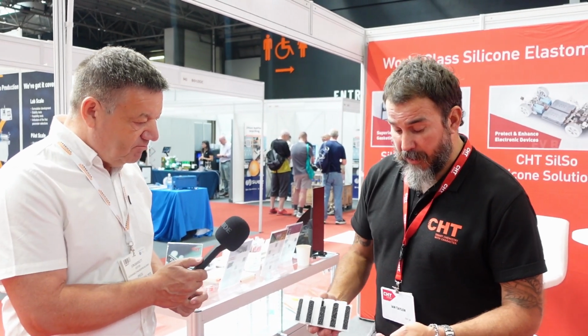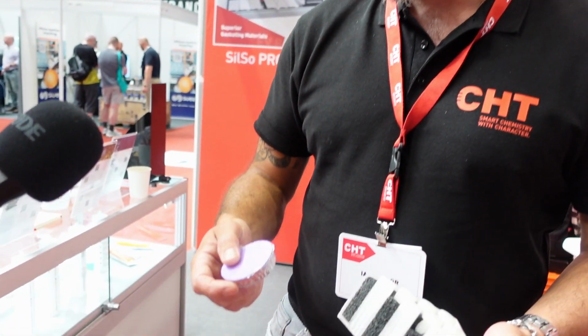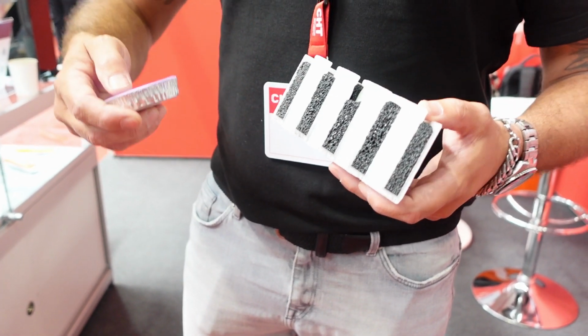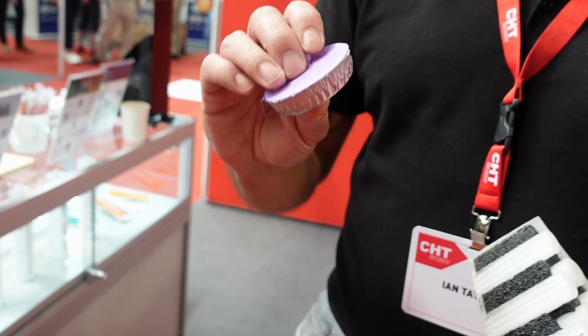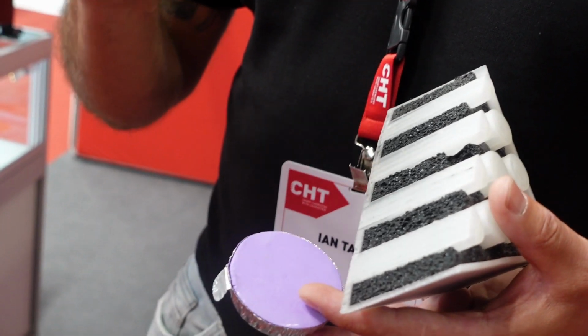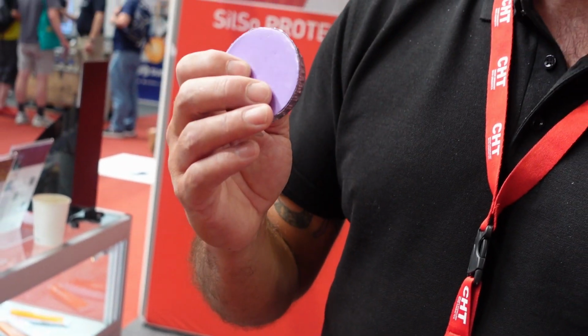Absolutely, John. So the company I represent is CHT UK. We manufacture silicones for all different types of environments. And what we're seeing at the moment is a massive influx in lightweight applications. Initially, we developed a product similar to this, which is for lightweight products at depth for water blocking of umbilicals and cables and things like that. So inside of this is glass beads, very lightweight, around 0.58 density. But because there's glass beads in there, it can withstand some serious pressure at depth. So that's what it was originally designed for.